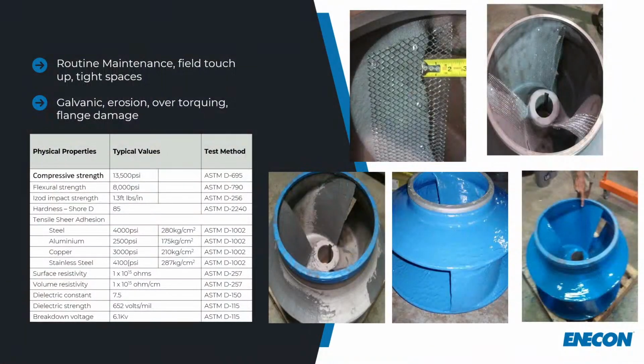Some pump repair facilities do this. I work with quite a few of them. This is the ceramic paste right here. They're applying that. They can always grind that down once the material sets up. And then they're going to do 2 coats of a ceramic epoxy right there for a wastewater application. Potable water, you're using generally a chemical protection epoxy. It's going to be a little bit thinner. For a wastewater application, I'd always specify a ceramic epoxy, 2 coats at about 12 mil thick per coat.